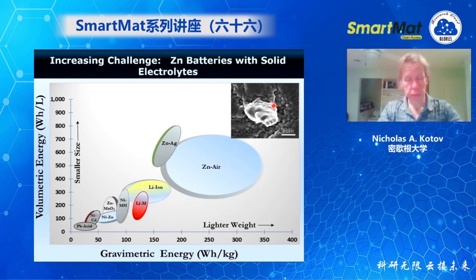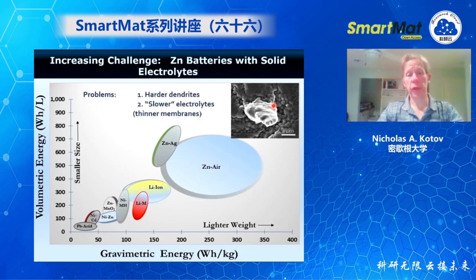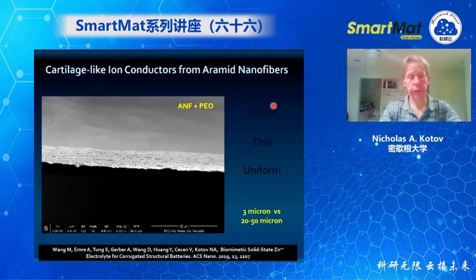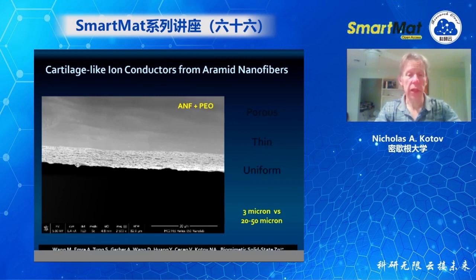Prevention of the growth of zinc dendrites is much harder than for lithium because it's harder, and also the electrolytes that are used in zinc are actually not allowing the divalent ion of zinc to transport fast. So the charging is not that fast. So we decided that we need to try this challenge, and we were able to address it.